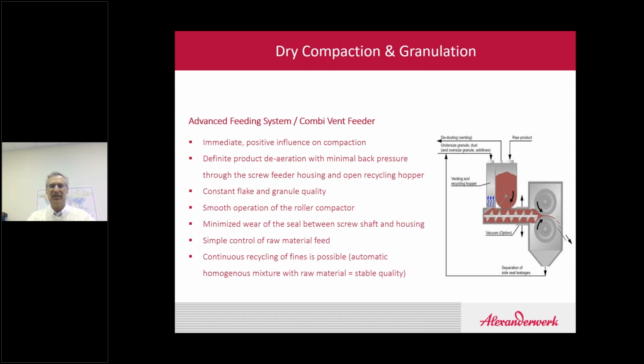Remember, we're compressing the material, compacting the material, we're removing air from the material. And interestingly enough, with this particular design, the air actually travels back through the center of the feed screw and then exits out the back section of the combi vent feeder. It's an interesting phenomenon to watch, and it works very, very well. It's actually a patented design from Alexanderwerk.